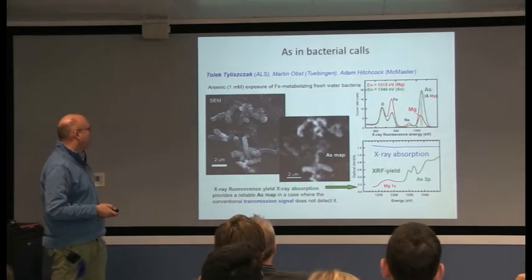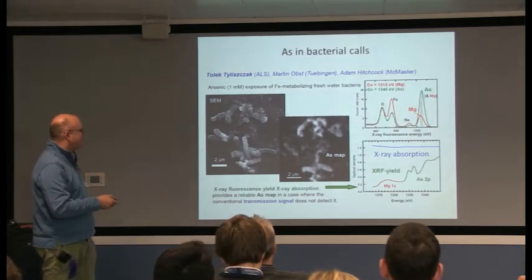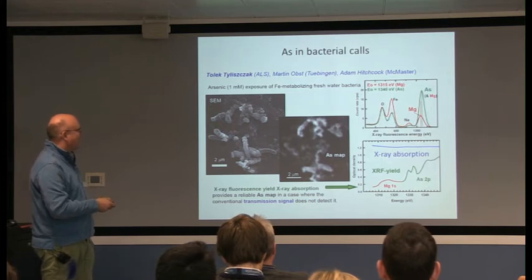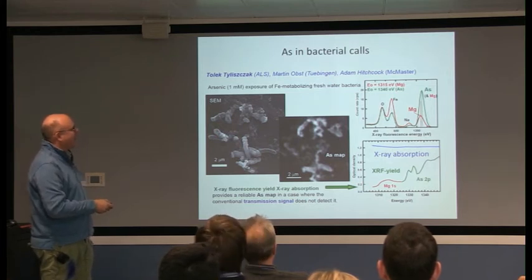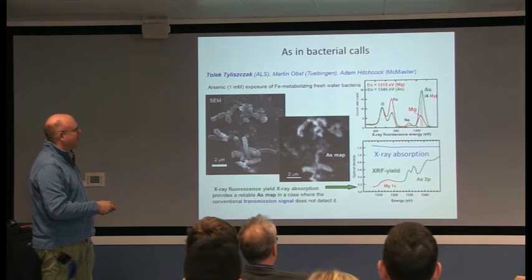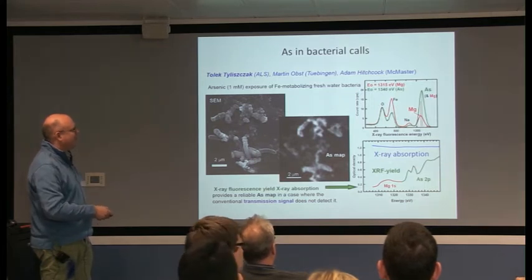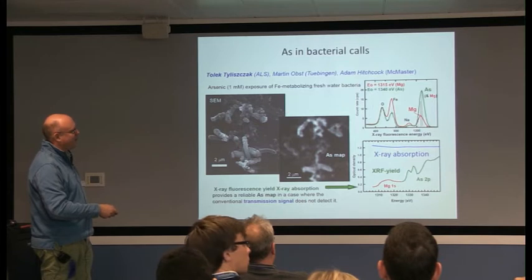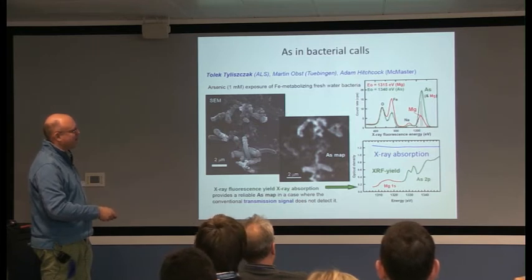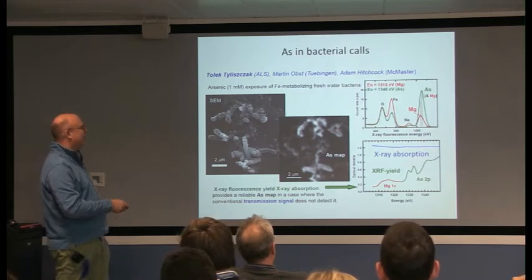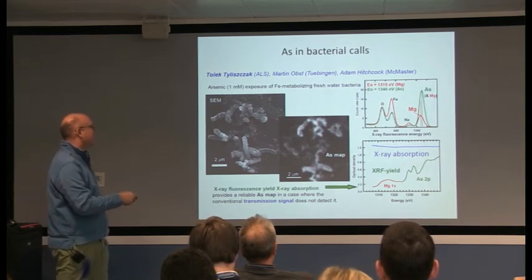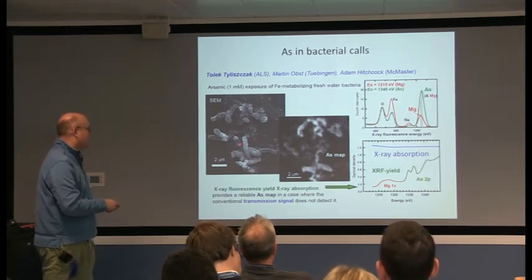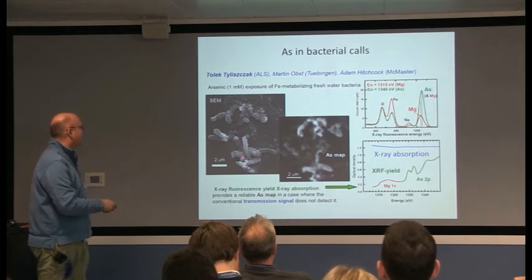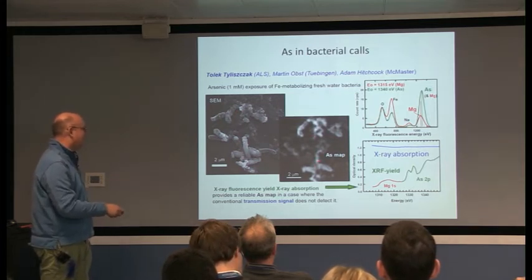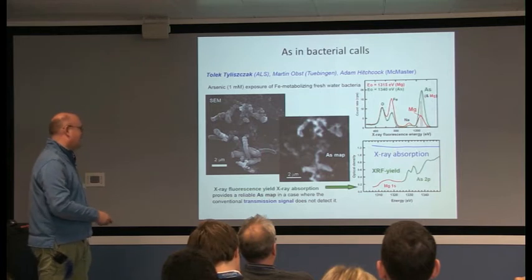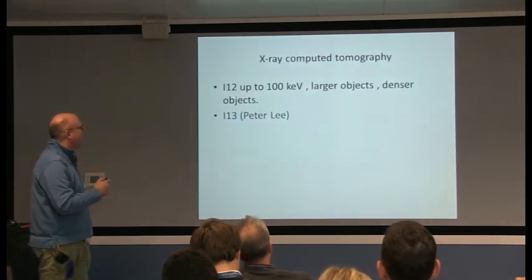There's a similar example on arsenic on bacteria. This is a fluorescence example. You've got a transmission spectrum here, the X-ray absorption, so you almost see no arsenic, but if you do the fluorescence yield, you can see the arsenic, because if you're really dilute, this arsenic is associated with these iron metabolizing freshwater bacteria. Here's the arsenic map, and here's the SEM image, and you can see that the arsenic is clearly going around the side of the bacteria, while in transmission you'd never see that.